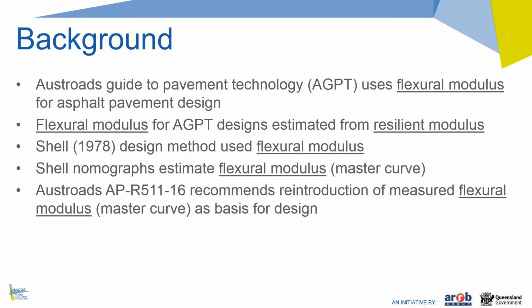And some of the people listening out there may be familiar with the Shell nomographs, which can be used to predict modulus from binder properties. Those nomographs are actually also based on flexural modulus values. So use of the flexural modulus is completely consistent with our current design method. And an Austroads project that we've recently completed also recommends the use of a flexural modulus master curve, much the same way as we've just discussed here, as the basis for design within the Austroads guide. So we're just implementing it early, as it were.